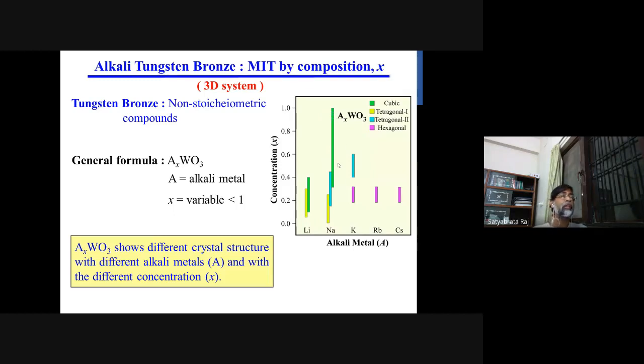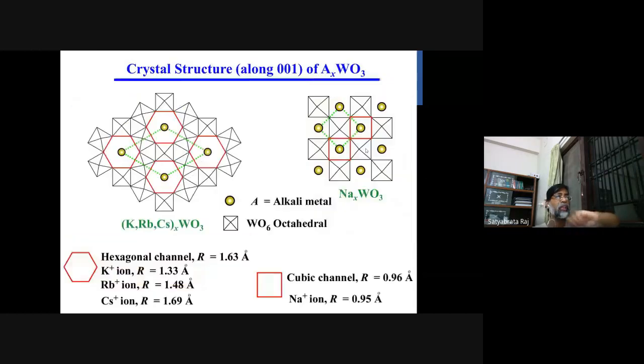Out of these alkali metals, the more studied alkali tungsten bronze is the sodium doped one, because it reaches the cubic phase, which is easier to understand and to develop models to understand the metal insulator transition. And let's see why, though all alkali metal doping should behave in a similar way, the higher atomic number elements crystallize in the hexagonal, whereas the smaller ones like lithium and sodium go towards cubic. That is the first question one should ask, and we have explained it in this way.